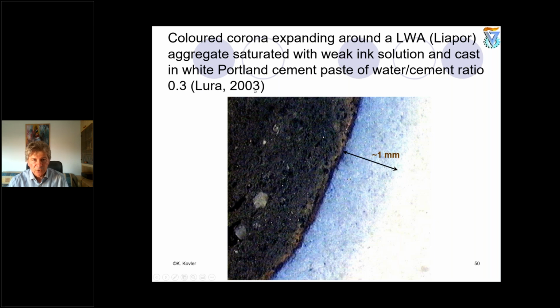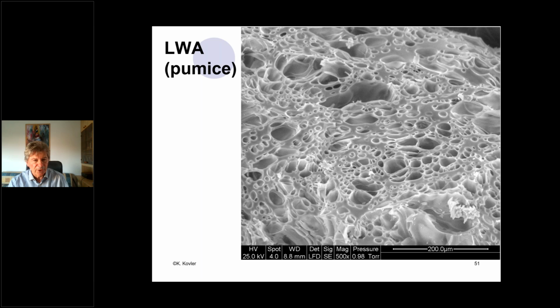Lura in 2003 tried to measure how deep, how far this water accumulated inside the particles of the porous aggregate can penetrate outwards. So he used ink solution, and then he measured, for example, 1 millimeter is quite something. But for me, it's not a very accurate experiment because we don't know exactly what the kinetics were. So we don't have any idea when this water was liberated from the particles. But for sure, it can liberate and penetrate too far. We are speaking about millimeters.